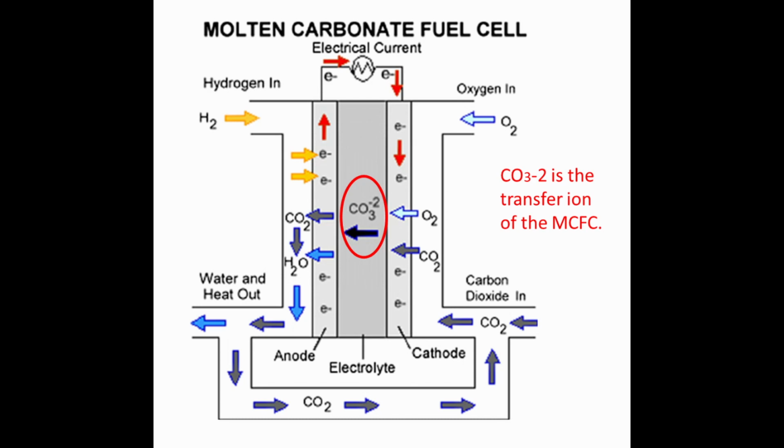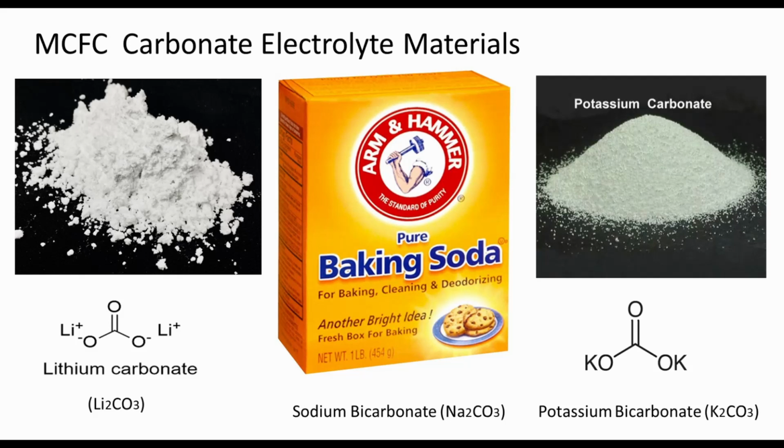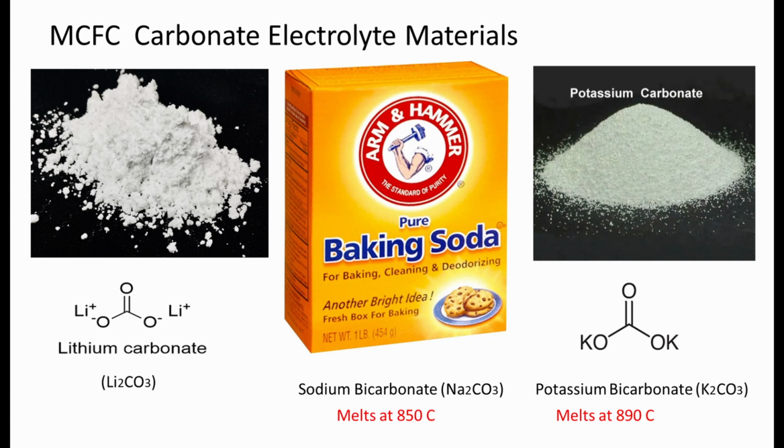The transfer ions in an MCFC are carbonate ions, CO3 double negative. The carbonate electrolyte material can be potassium carbonate or sodium carbonate or lithium carbonate or a mixture of all three carbonates depending on the manufacturer's recipe. The melting temperatures of potassium carbonate and sodium carbonate are 890 degrees Celsius and 850 degrees Celsius respectively.